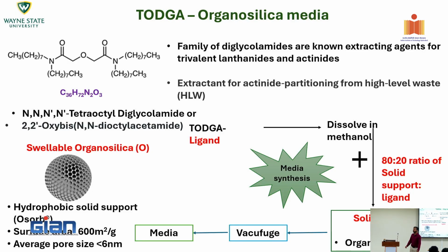It belongs to the diglycolamide family, and it is conventionally used in many national laboratories for separating uranium and separating nuclear waste. What is special about this is that it works only in extremely acidic conditions. It chelates very well in extremely acidic nature. That's why we chose it as the primary ligand, or primary adsorbent material, to selectively remove gadolinium from the urine.